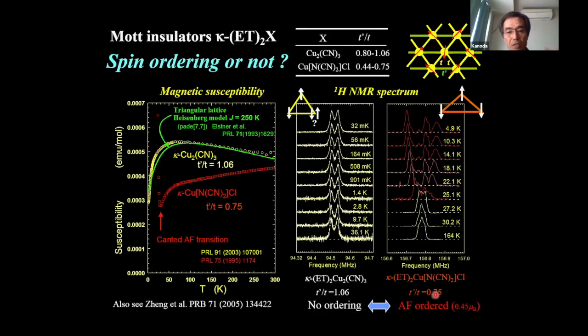Please take a look at the old data of these materials. In the deformed triangular lattice, this is the NMR spectra, a proton NMR spectra. You see this single line at high temperatures split below 27 Kelvin. This is the clear indication of the antiferromagnetic ordering.